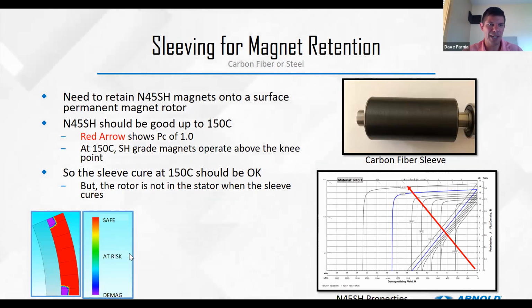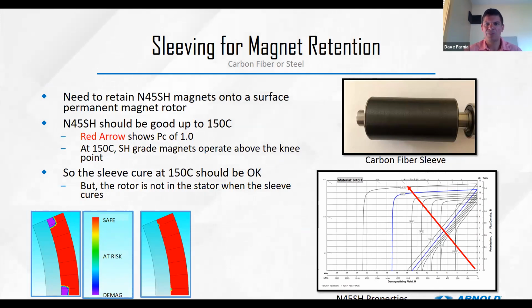Since the rotor is not with the stator, it's pushing that permeance coefficient much lower. So our actual permeance coefficient of the rotor is probably somewhere down here. At that point, now we are seeing some demag in those corners. So if we said, well, we want to operate at 150 degrees C and we need to sleeve it, perhaps we can use some type of magnetic keeper, wrap it with steel, and increase the permeance coefficient of our magnets, or we can switch to a higher grade. The SH grade should be good to 150. The UH grade should be good to 180 degrees C. So sometimes we have to over-design the magnets based on the manufacturing process.